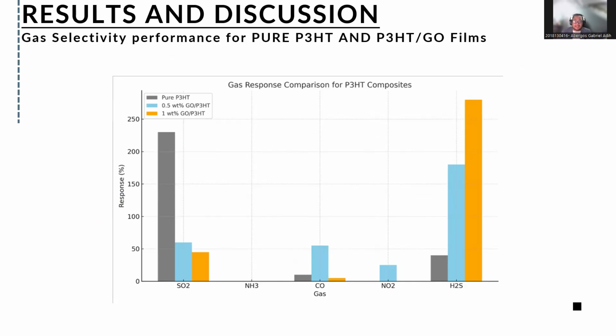These groups act as active adsorption sites, promoting stronger interaction with H2S and facilitating efficient electron donation to the sensing film. The high surface area of GO combined with these functional groups enhances gas adsorption, while pi-to-pi interaction between GO and P3HT improves charge mobility and sensing response. Although GO enhances H2S sensitivity, it can reduce SO2 detection due to the possible blocking of active sites on P3HT and changes to its electronic structure. Overall, P3HT GO composites demonstrate superior selectivity for H2S, while pure P3HT remains more